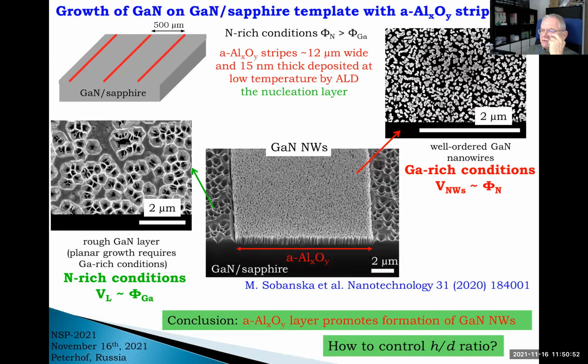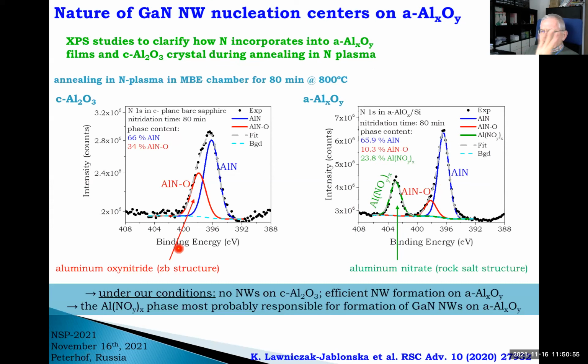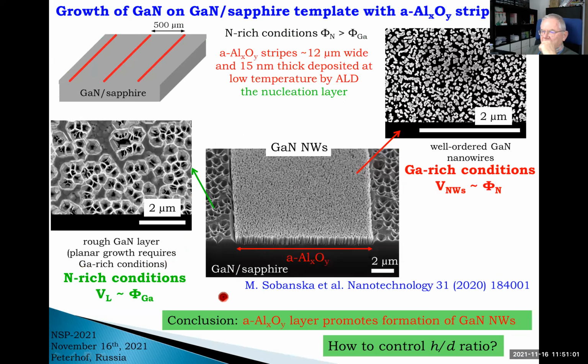Okay, I showed you that aluminum oxide is efficiently used for growth of nanowires, so why not use it for selective area growth of such wires? And I will show you two examples of this efficient nucleation layer. In the first example, we just take a gallium nitride substrate with aluminum nitride or aluminum oxide stripes, and we just grow nanowires at typical growth conditions.